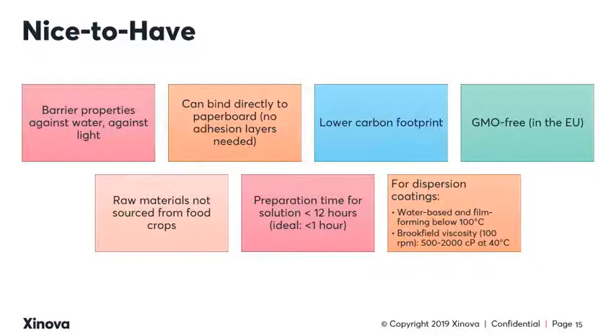It's also ideal to lower the carbon footprint. As mentioned, the circular economy, it's good to lower the carbon contribution from that material. It should be GMO-free. It should also not use raw materials that are sourced from food crops, meaning it wouldn't be food competing. The preparation time for a solution of this material should be less than 12 hours and ideally less than an hour. And finally, for dispersion coatings, there's a couple of things to note. It should be water-based and film forming below 100 degrees Celsius. And the Brookfield viscosity should be 500 to 2000 centipoise at 40 degrees Celsius.